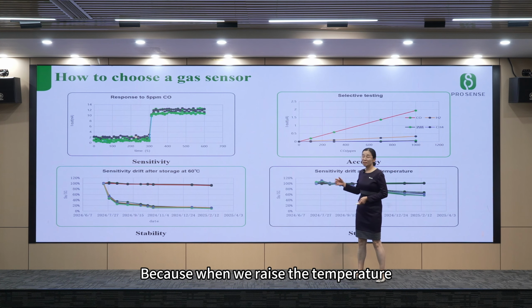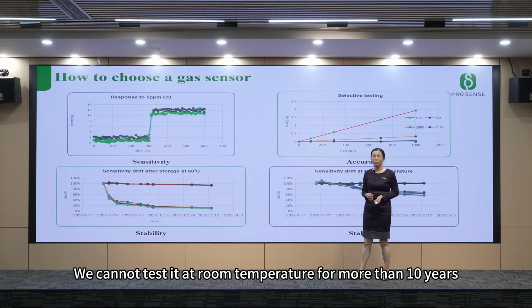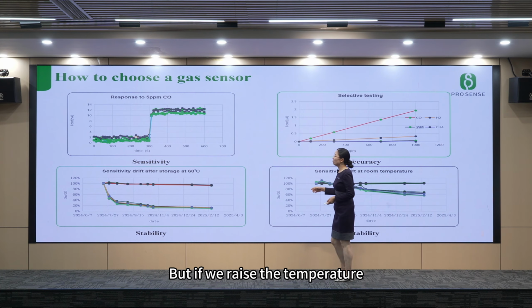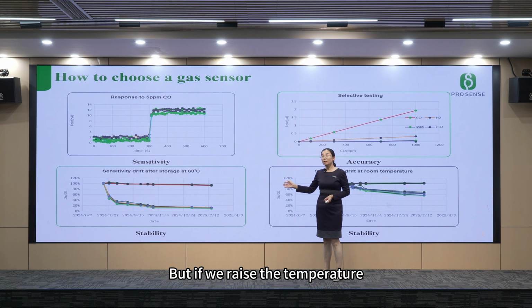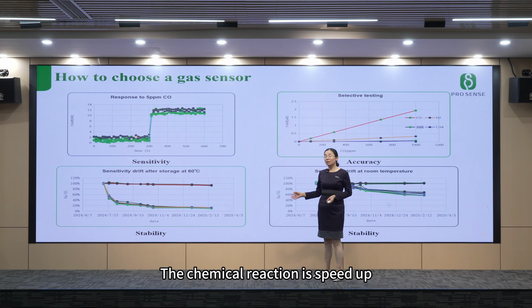Because when we raise the temperature, we are doing an acceleration test. If we say a sensor has 10 years of life, we cannot test it at room temperature for more than 10 years. But if we raise the temperature, the chemical reaction is sped up, and it can give us some index of the lifetime. So please make sure that you use the right method to evaluate the sensor.